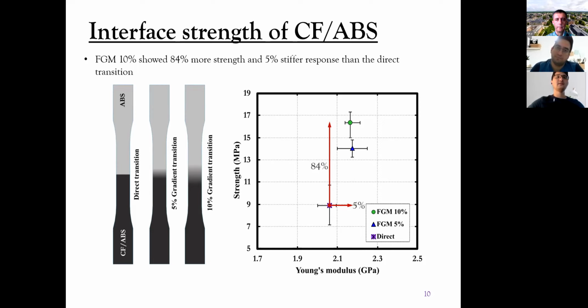This shows that if we keep increasing the gradient length inside the gauge region, we can get more strength values. We can enhance the material property. And also the material property is enhanced 17% at 10% FGM than at 5% FGM.